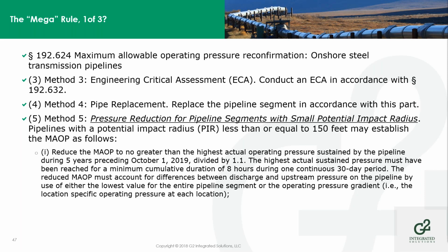Pressure reduction for pipeline segments with small impact radius, with small PIRs. You can reduce the MAOP to no greater than the highest operating pressure sustained during the previous 5 years, divided by 1.1, as long as that pressure was a cumulative period for an 8-hour period during one continuous 30-day period.